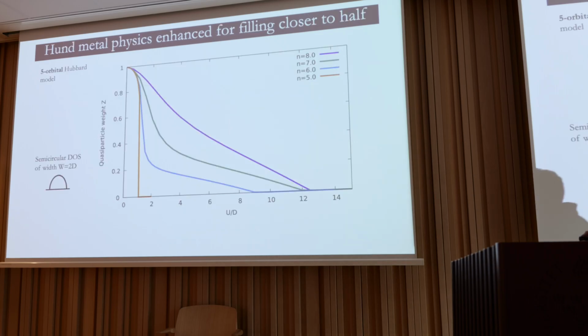What I'm trying to highlight is that that's not all the story, because when you go towards half filling, you go towards a phase which is also Mott insulating, and you enhance this Hundness. So the Mott insulator enhances this Hund metal phase. These are the quasi-particle weights for a 5-orbital Hubbard model with 8, 7, 6, and 5 electrons, and you see that this S-shaped behavior gets more and more enhanced the more you go towards half filling.